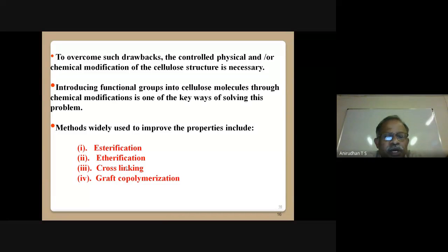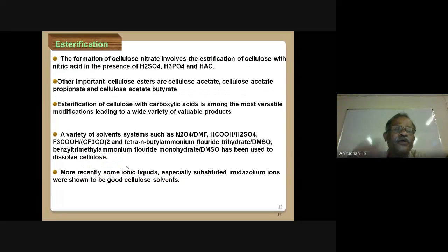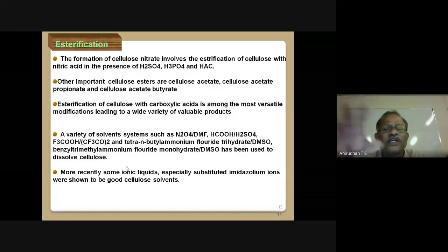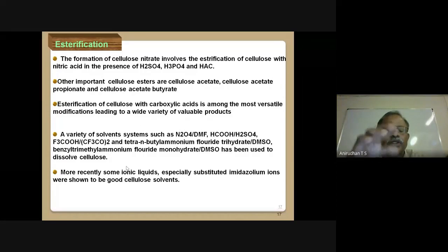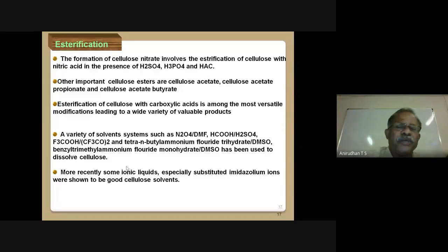What are the methods? Esterification, etherification, cross-linking, graft copolymerization are the recently developed methods to improve the existing properties of this cellulose. So what process is taking place in esterification? Cellulose is converted into cellulose nitrate after treating with nitric acid, in presence of sulfuric acid and phosphoric acid or acetic acid. These are very simple techniques to prepare esters of this cellulose for wide applications.